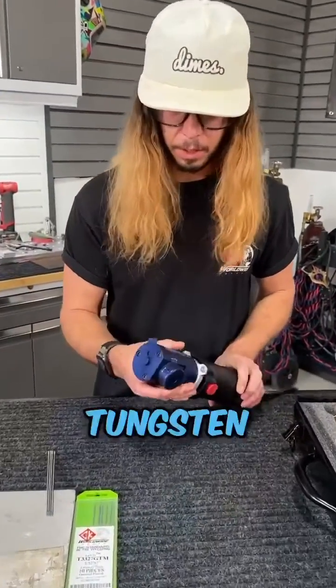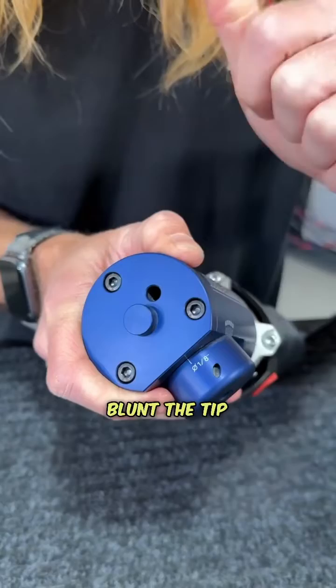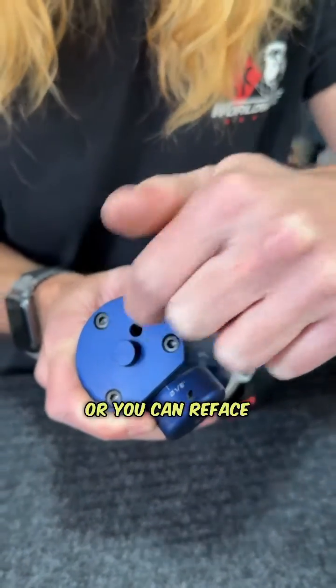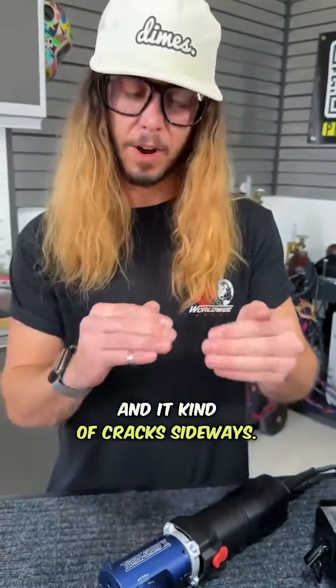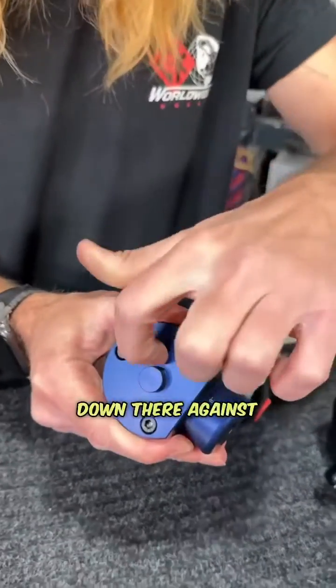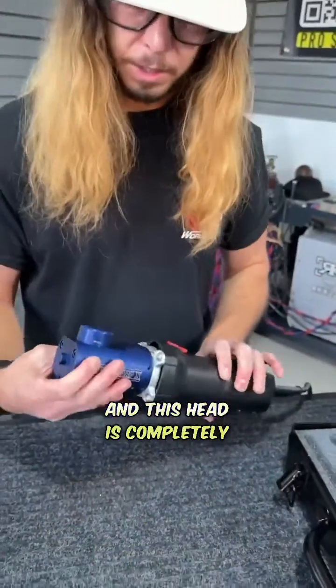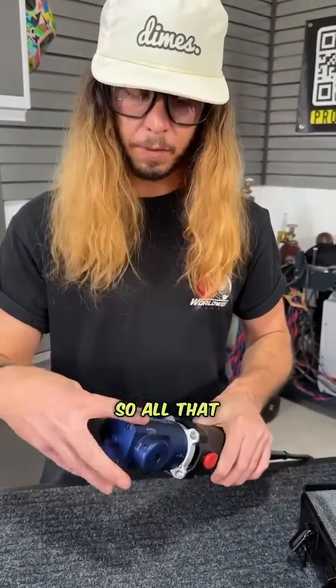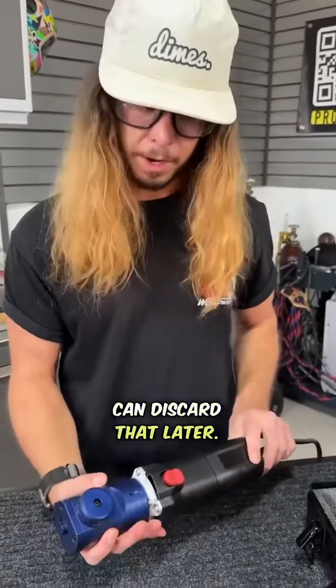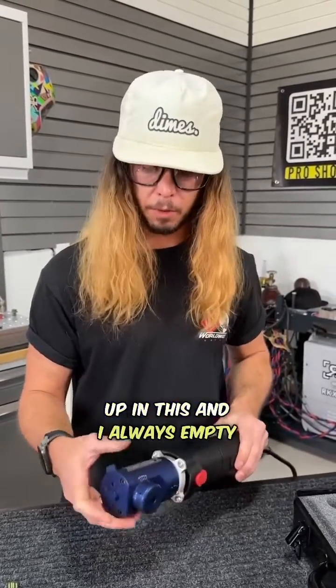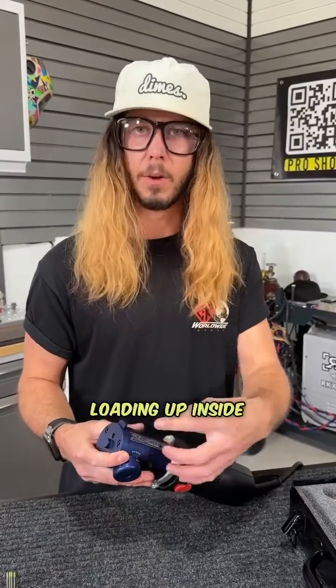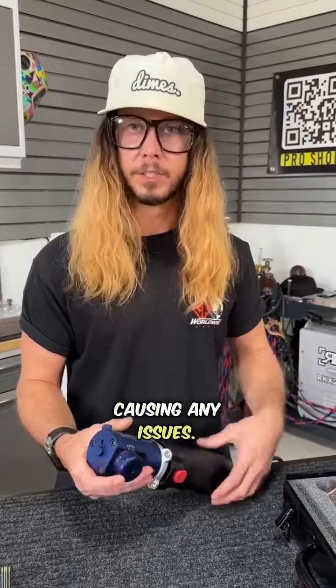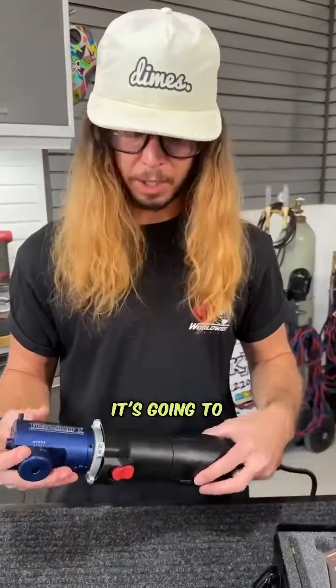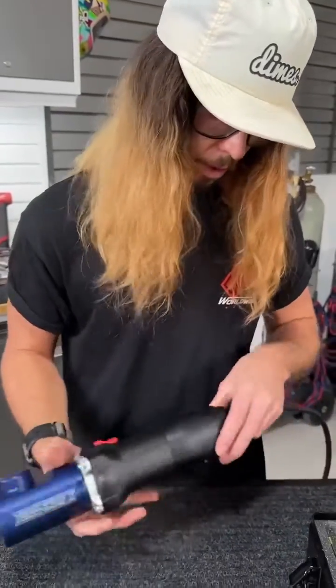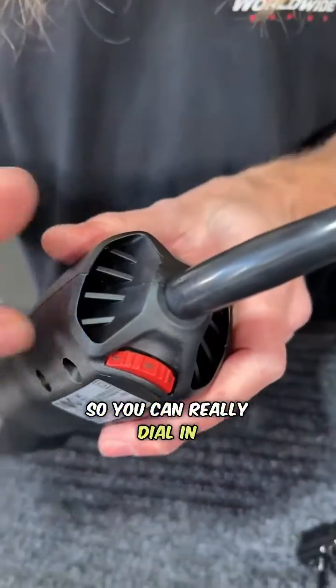But those are some of the common grind angles that I use on my tungstens. Another thing I really like about this tungsten grinder is it has a slot in the top that you can blunt the tip of your electrode if you need to, or you can reface it if you try to break the tip off and it kind of cracks sideways. You can reface that tungsten down there against the diamond wheel. And this head completely contains all of the grinding dust. So all that dust is contained inside the head, and then we can discard that later. I really like to make sure I don't let the dust load up in this, and I always empty this out pretty frequently. You don't want tungsten loading up inside around that diamond wheel and causing any issues. The more you take care of this tungsten grinder, it's going to last you for years on end. It also has a variable speed control, so you can really dial in your grind to the speed that you like to grind it at.